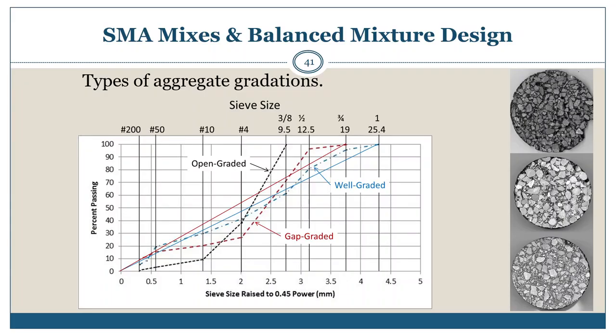An open graded aggregate blend contains only a small percentage of small-sized particles. This results in more air voids and much higher voids in the mineral aggregates because there are not enough small particles to fill in the voids between the larger particles. The open graded relationship is shown by the dashed black line. The curve is near vertical in the mid-size range and flat and near zero in the small size range. The gap graded has higher voids in the mineral aggregate, requiring higher asphalt content to reach the same design air void level in comparison to the well-graded aggregate blends.